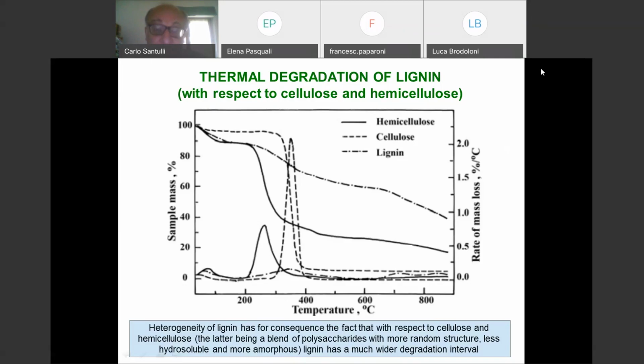But apart from these considerations, in other cases, you can see that with hemicellulose you have 20% left, and with lignin you have a lot left. Even at 800 degrees, probably it's not finished even at 900. Something will disappear yet, and in the end you get just carbon, graphite, basically. But not oriented, just carbon, really.